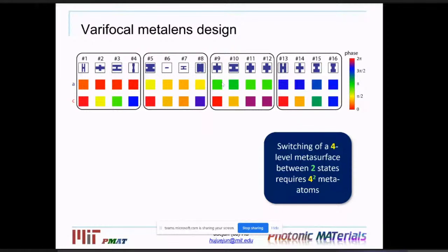Each of these meta-atoms imparts a different phase delay in the amorphous and in the crystalline state. So we're encoding this phase delay using different color codes here. Red means 0 phase delay, yellow is half pi, green is pi, and blue is 1.5 pi, so this covers a full 2 pi phase range. Now, if you look at the amorphous state phase delay here, we group these 16 meta-atoms into four different groups. Within each group, the meta-atoms exhibit the same color in terms of phase delay, so each group exhibits essentially the same phase delay behavior in the amorphous state. Now, if we switch to the crystalline state, you see that within each group, 4 different colors show up, indicating that we can translate the same phase delay in the amorphous state into a full 2 pi phase coverage in the crystalline state. So with the combination of all 16 meta-atoms, we can cover the full 2 pi phase range in both the amorphous state and the crystalline state.